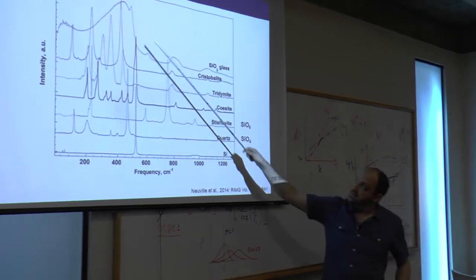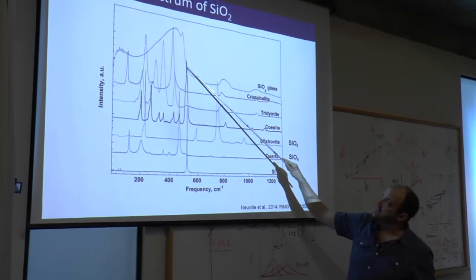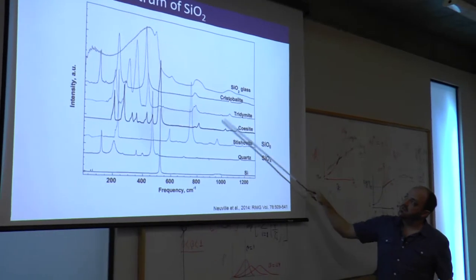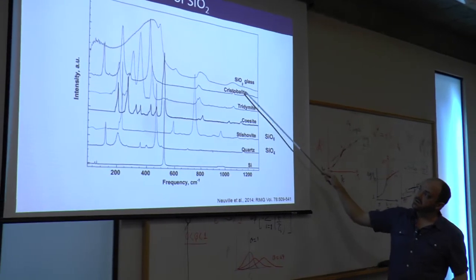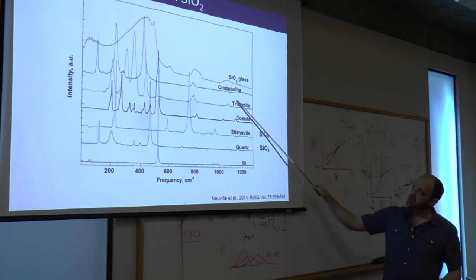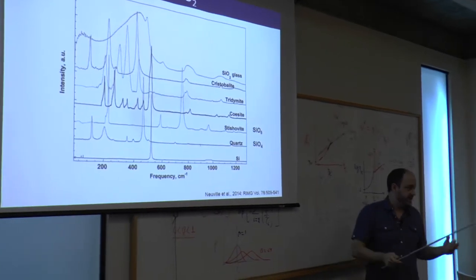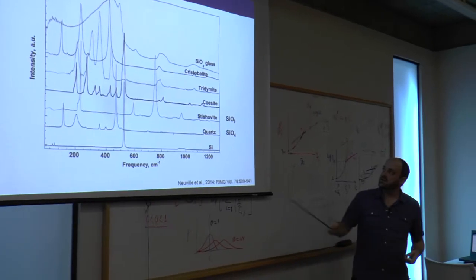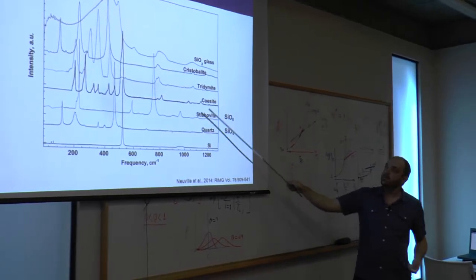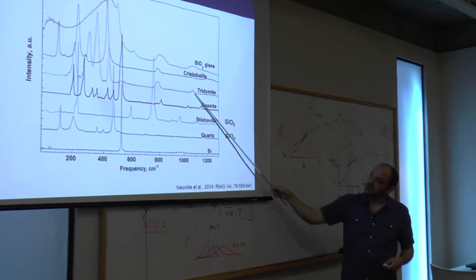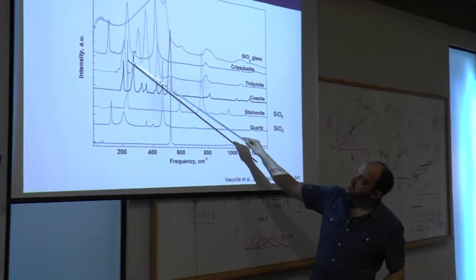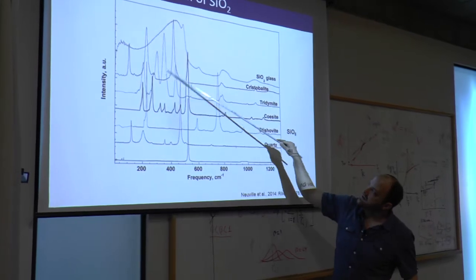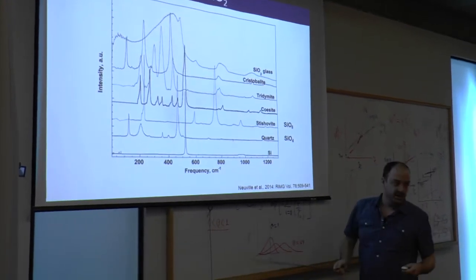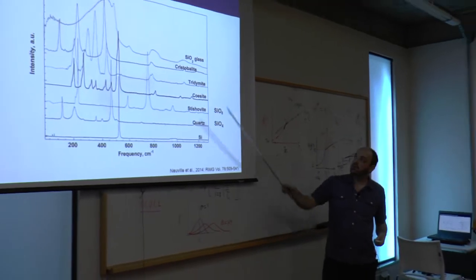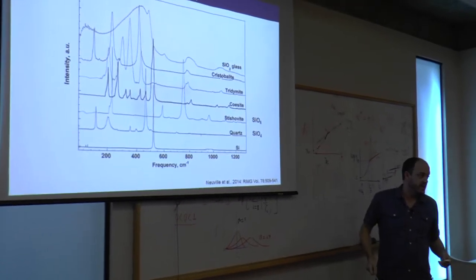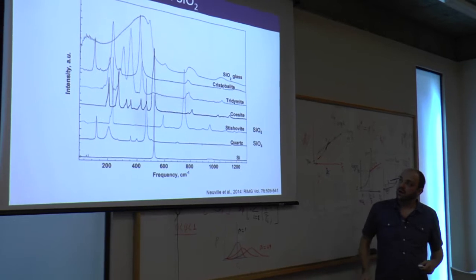And they said, this envelope here is awfully similar to some of these different polymorphs, cristobalite and tridymite especially. And when you look with different techniques, you can see that some aspects of pure silica resemble cristobalite quite well, and some aspects resemble tridymite quite well. And you can see that their most intense features happen to coincide with this broad band here. So various people have proposed a cristobalite or tridymite-like structure. Both of these have 6-member rings in them.